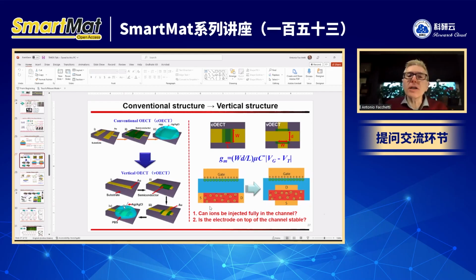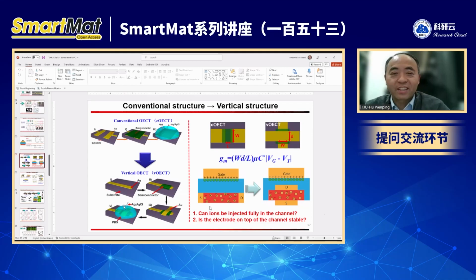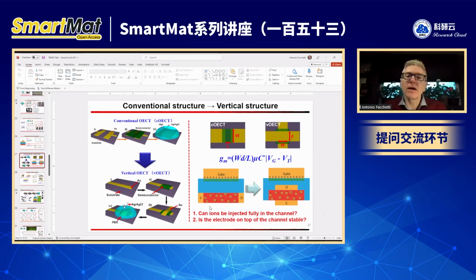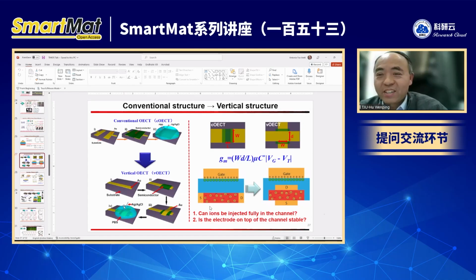Yeah, you usually really need a very small channel length, and the reason is that the bias you apply through the gate is very, very small, just less than 1 volt. So if your source and drain are too far apart, you don't get an electric field strong enough to move the ions. So you have to have a very small channel. If you make it too big, you just measure nothing. Okay, thank you very much, Antonio.